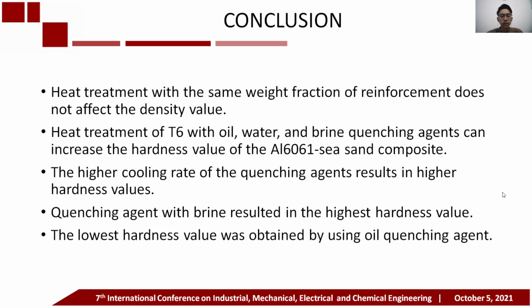In the end, we come to the conclusion. Heat treatment with the same weight fraction of reinforcement does not affect the density value. Heat treatment of T6 with oil, water, and brine quenching agents can increase the hardness value of the Al6061-sea sand composite. The higher cooling rate of the quenching agents results in higher hardness values. Quenching agent with brine resulted in the highest hardness value. The lowest hardness value was obtained by using oil quenching agent.